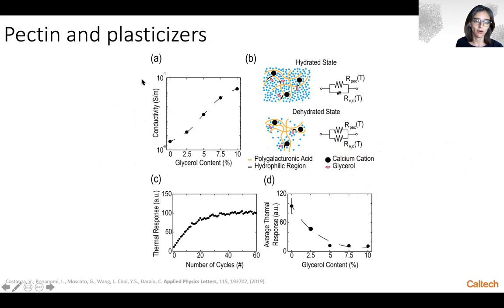Unfortunately, this significantly affects the average thermal response, which is the diagram you see on plot D, suggesting that although the use of plasticizers could improve the mechanical response, it is not ideal because it reduces the response to temperature.